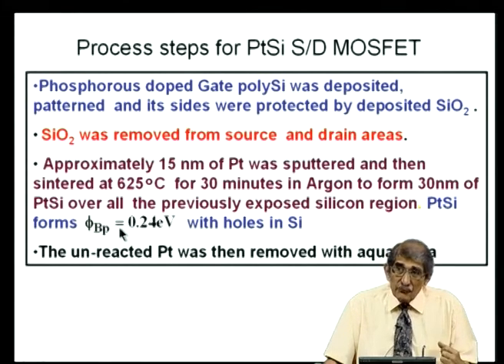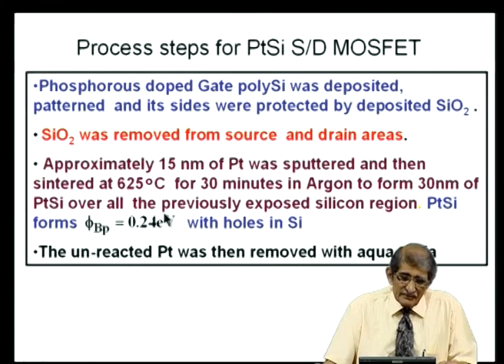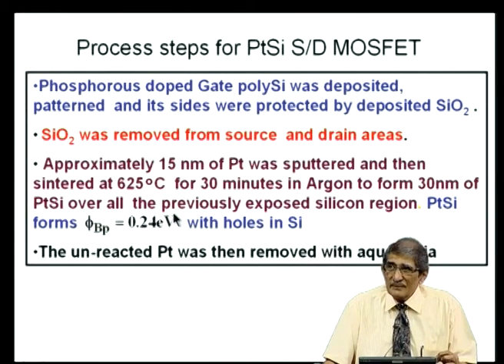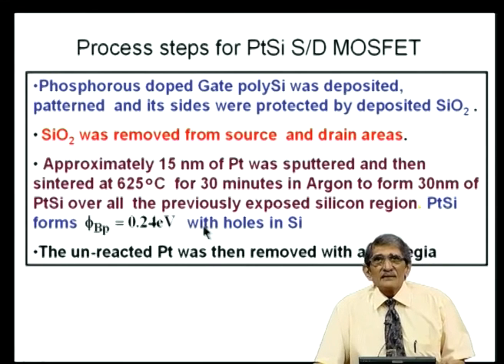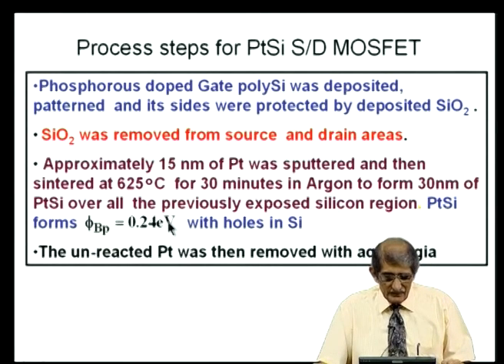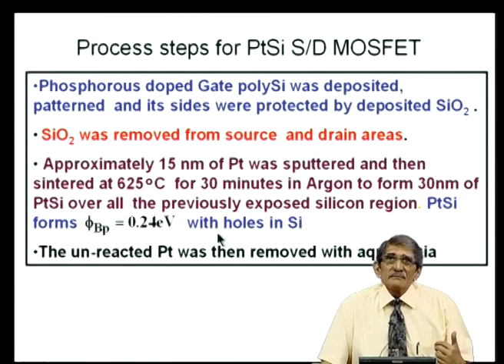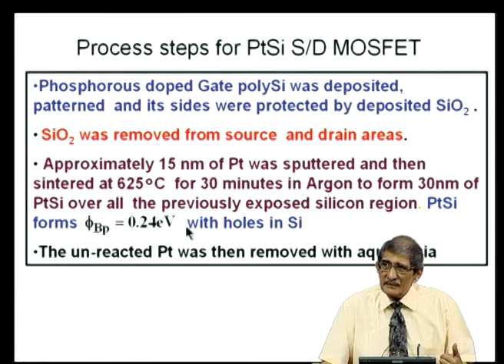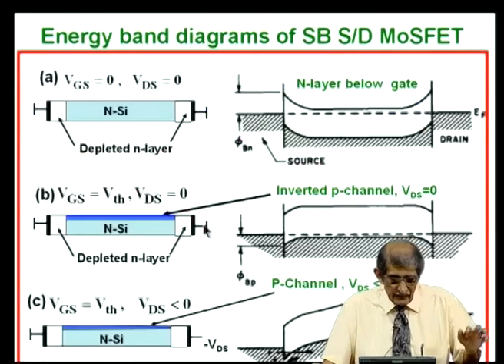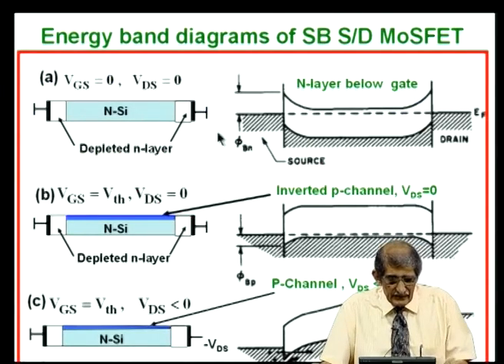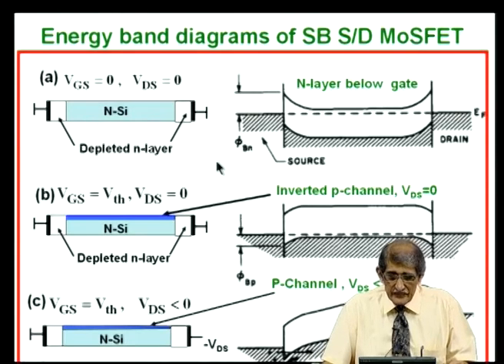The nice thing is that the barrier height for holes, for the P channel, is very low, about 0.24 electron volt. It is close to the Fermi level pinning type. That means you can actually make working transistors, because the barrier height for holes is very small and the supply of holes is very large. Now, let us quickly take a look at the energy band diagram.